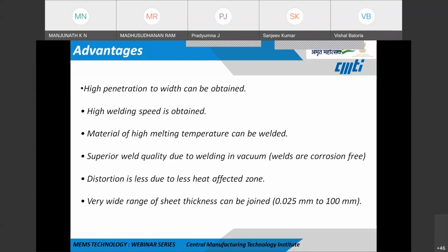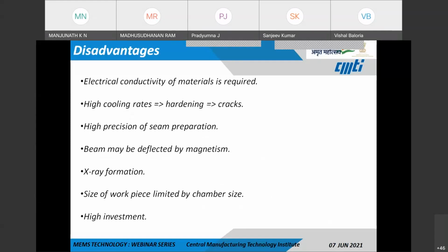up to 100 mm. Some of the disadvantages of these weldings are that the material has to be electrically conductive, and there are high cooling rates which tend to have a hardening effect, and sometimes they may also crack. And high precision of seam preparation is required, that is, surface preparation is very much required when we are going for a weld. And the beam may be deflected by magnetism. So sometimes when we use magnetic materials, the beam may not fall on the intended position, as it will be deflected by these magnetic fields.